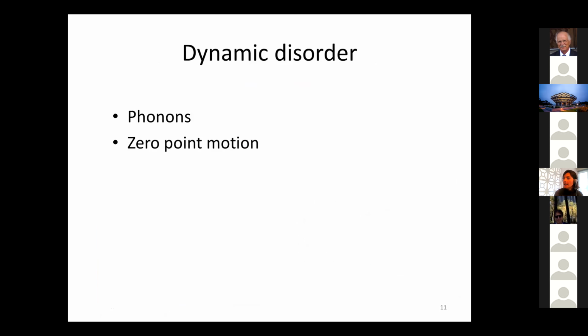Now, there are two types of dynamic disorder that we have in materials. There are phonons, whose amplitude is temperature dependent, and then there is zero-point motion. This zero-point motion is something that we are very interested in, and I'm going to talk about it more today. These are quantum mechanical effects that exist at zero temperature, which means that even if you totally remove the axis of temperature and stay at zero temperature, you can still get phase transitions by changing other parameters like magnetic field, electric field, or pressure.